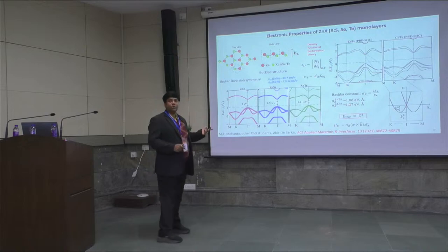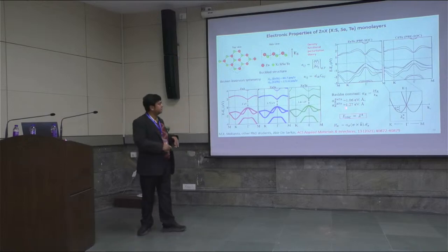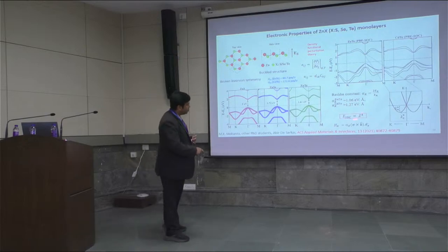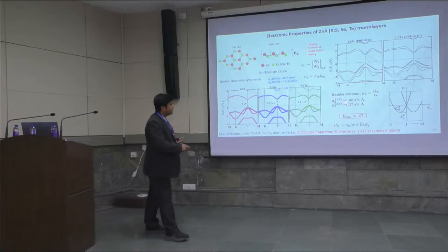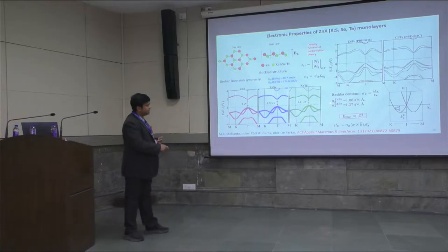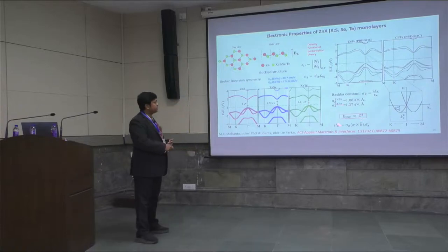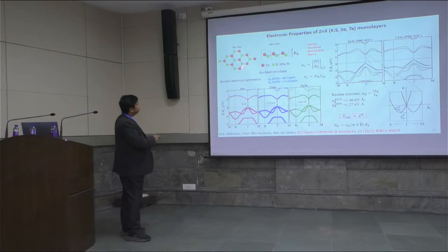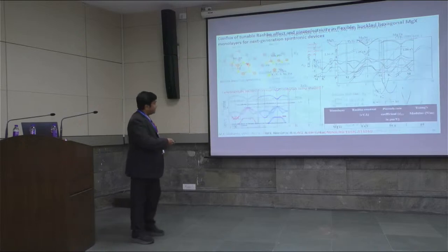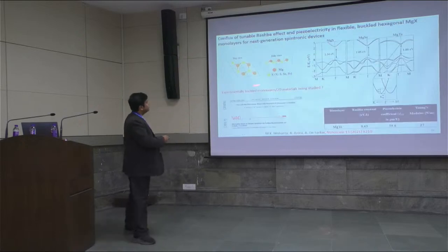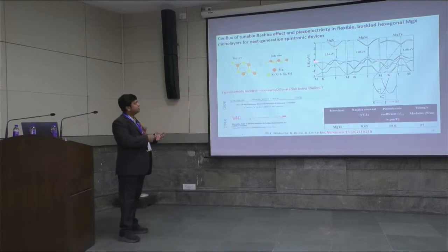And you need a high Rashba constant for spintronics application. Also, we are aware that spin orbit coupling is proportional to Z to the power 4. So cadmium is heavier than zinc, and therefore it shows a larger Rashba constant. And also, because of the broken inversion symmetry, an out-of-plane electric field arises in CdTe and ZnTe. Likewise, the same thing applies to MgTe.